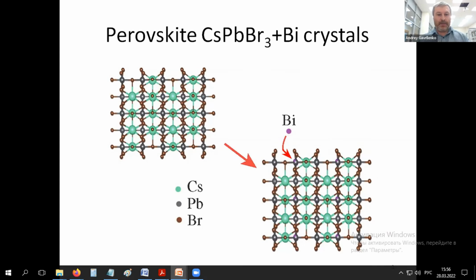Under standard operating conditions, perovskite materials are in a highly non-equilibrium thermodynamic state due to electronic excitation induced by either absorbed light or applied voltage. The interaction of free charge carriers or excitons caused by such excitation with defects can significantly change both the type of defects and their energy distribution.